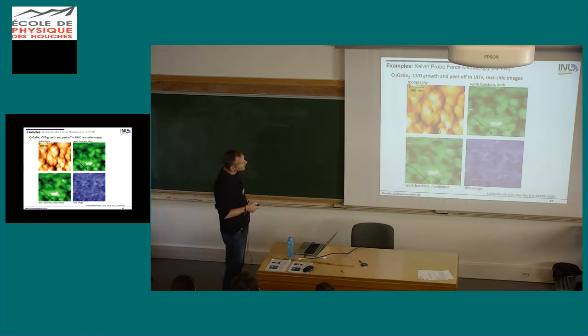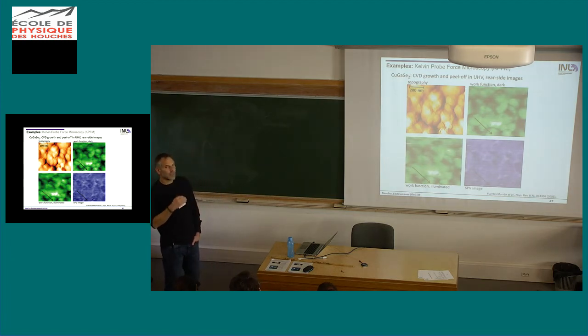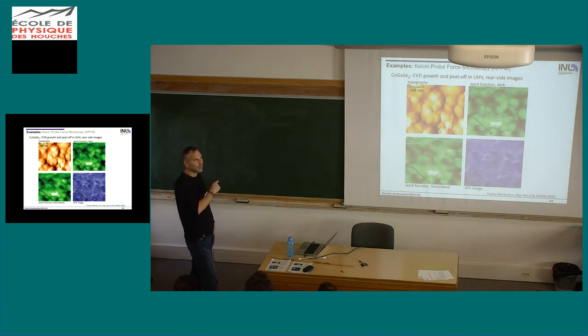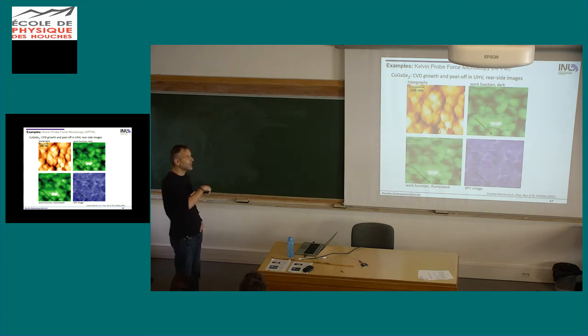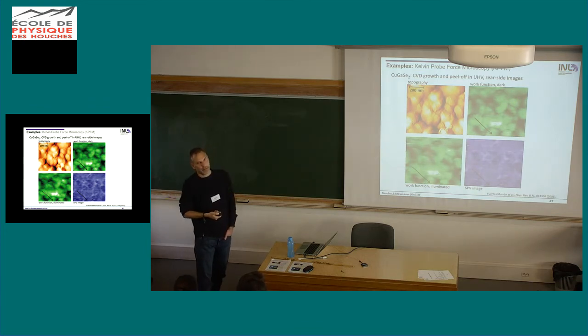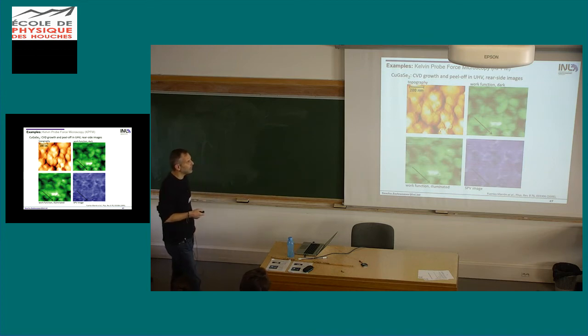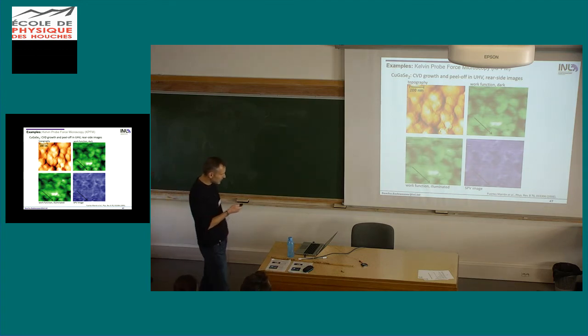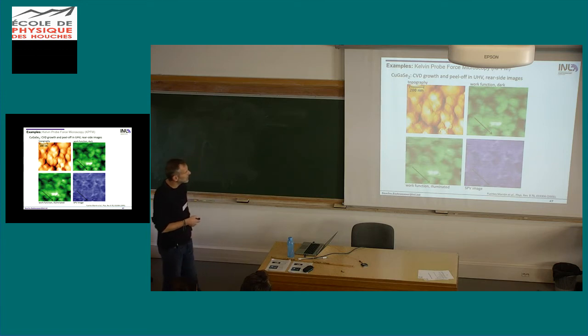And then if you image the work function, you see all these dark lines here. And these actually correspond to the grain boundaries. So it looks like the grain boundaries have a lower work function, which actually is in line with the results that we saw before. There's a band bending at the grain boundaries, and we saw that the work function goes down at the grain boundaries. So this corresponds very well to the other results that were done by scanning capacitance and conductive AFM. So then we can illuminate our sample, and essentially we see the same thing. So that's quite boring, but that's not completely true because there's no scale here on these images in terms of the Z scale, so there's the XY scale.